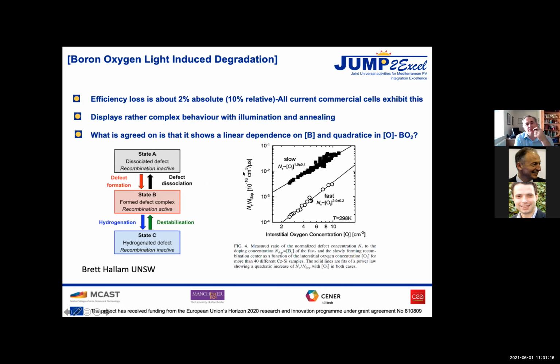Okay, so as I said before, the energy loss is around about 2% absolute or 10% relative, and essentially every current commercial silicon cell has some degree of degradation due to this boron-oxygen process. It shows rather complex behavior with illumination and annealing. What is agreed on, from a mound of evidence and work by people over many years, is that it shows a linear dependence on the boron concentration and a quadratic dependence on the oxygen concentration. So that suggests it's a compound of boron and two oxygens.